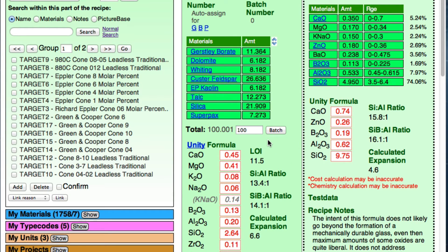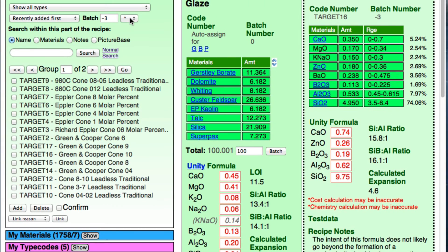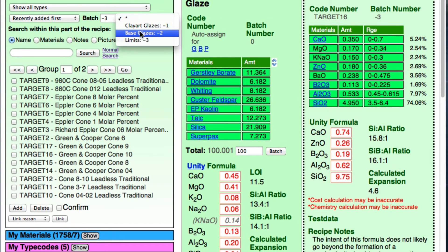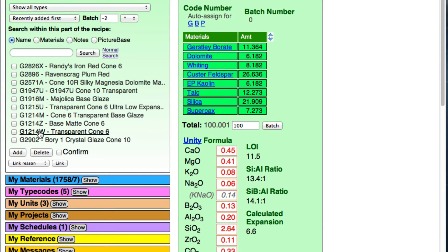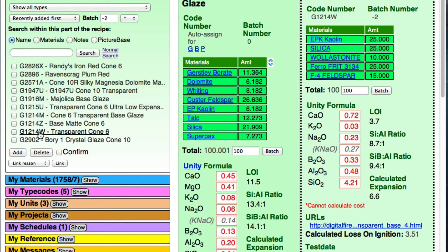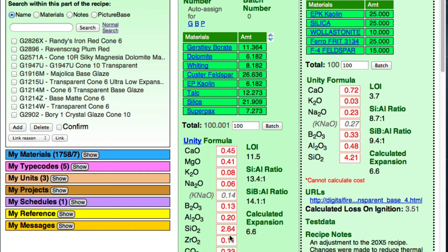How about comparing this with just a glaze — say a transparent glaze? I'm going to compare it with a cone-6 transparent glaze. I'll go to base glazes, click search, and pick this one. Look at this: 0.48 alumina. We've got 0.2 — our alumina is way lower than even a cone-6 glaze. And the silica is 4.2; we've got 2.6.